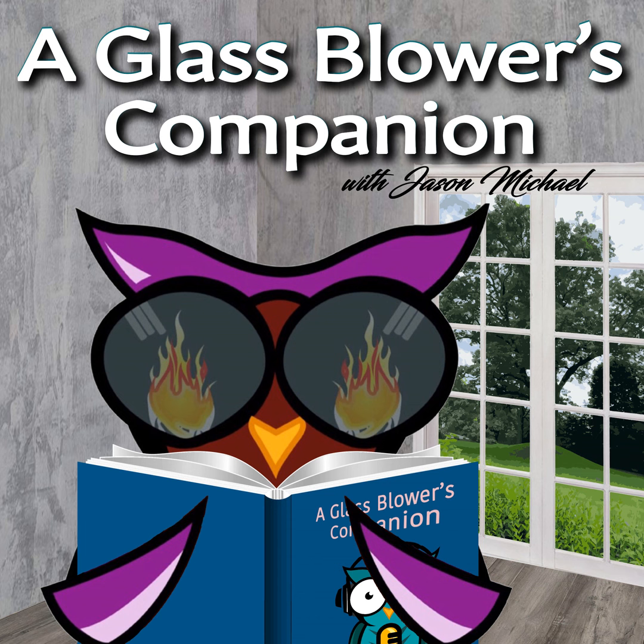That's why a lot of things can't be encased in borosilicate. That's why you can't encase certain stones and things like that. It's because if the COE is so much higher or lower, the stone is cooling too fast and will shatter whatever's encasing it. It's also moisture content as well. Like the real opals, a lot of them are too wet, and they actually will explode inside the glass.